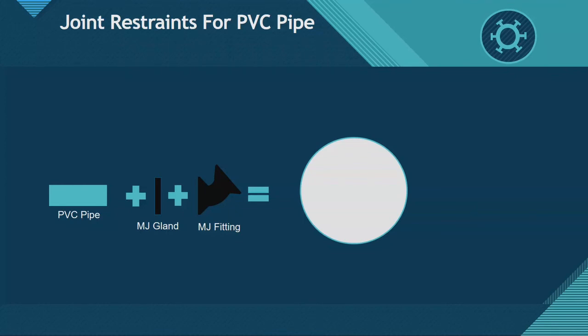So the first thing you have to do is put on your gland. That gland compresses the gasket. To compress it, you use T-bolts. Put the T-bolts in all the holes, except for the ones that line up with the holes of this. For those, you need to use longer T-bolts. Put the longer T-bolts in there. Normally this would be in 2 halves. I have it put together here just to make my life easier. Then you put your serrated restraint on there behind the gland, close enough that your longer T-bolt goes through there. Yeah, you can sort of see that, I imagine.